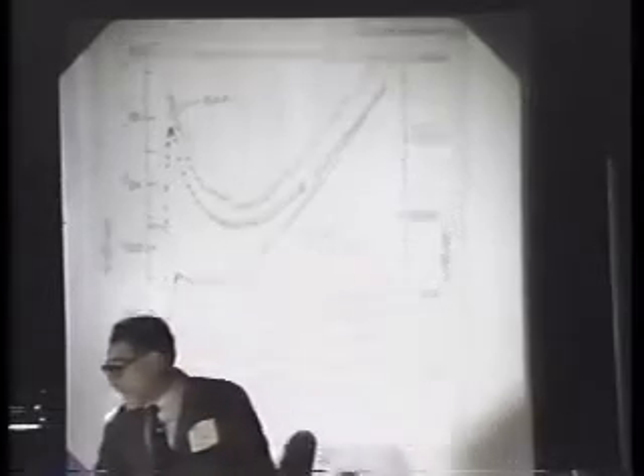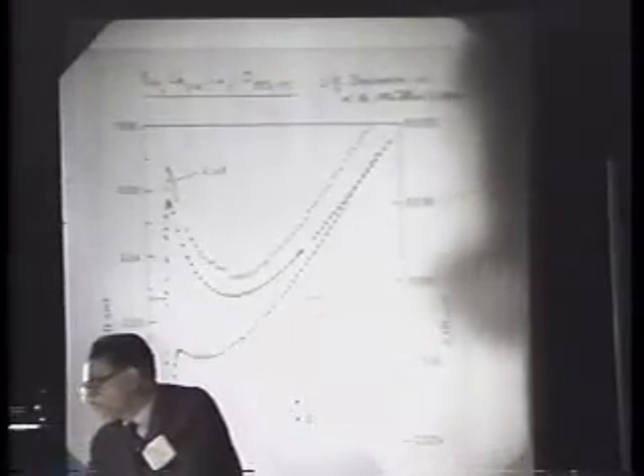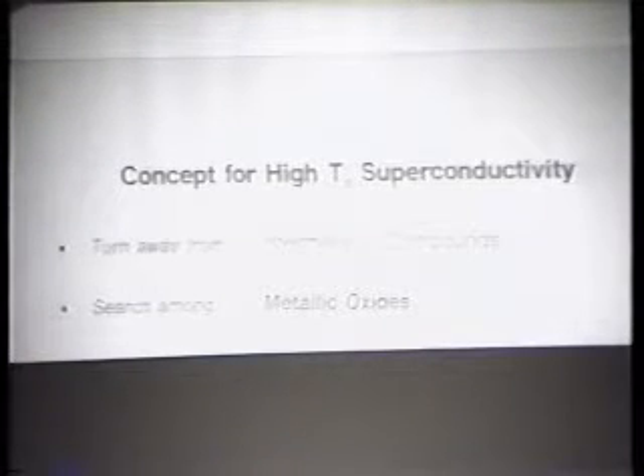Now, how did we find this material? Well, we had a concept for high TC superconductivity. Namely, I had come to the conclusion that one should radically abandon intermetallic compounds. There had been many groups who had tried to improve the TC in this area, but do a search in metallic oxides. What was the rationale of doing that?